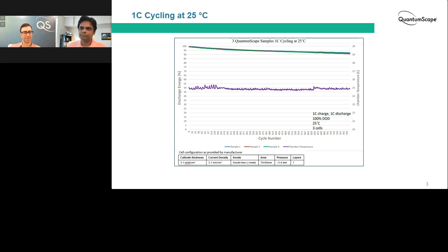Yeah. And one other point to orient the listener here is that a typical battery would be rated as end of life when it reaches 80% of its initial capacity. So one of the targets that our commercial automotive partners have given us is cycling to 80% after 800 cycles. And what you can see is that all of these cells are at around 90%. So their cycle life is expected to be even greater than 800 cycles, even under these relatively extreme test conditions.